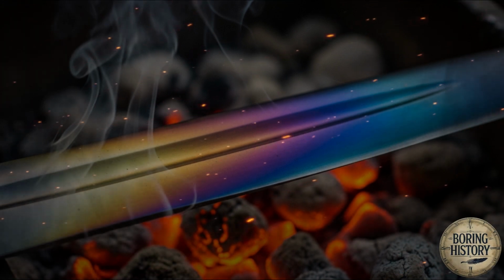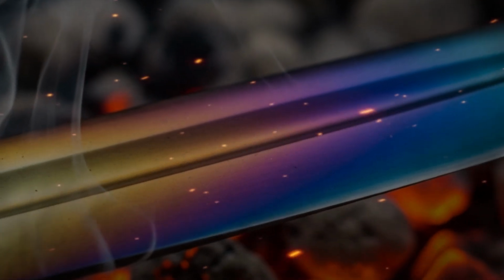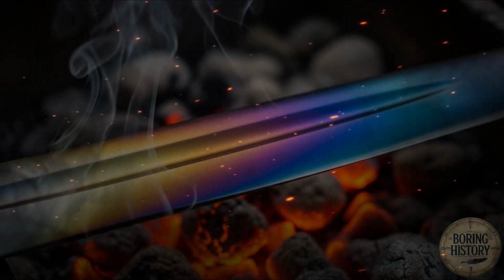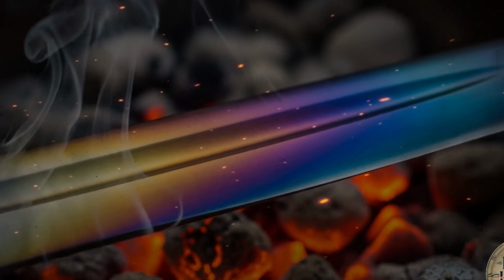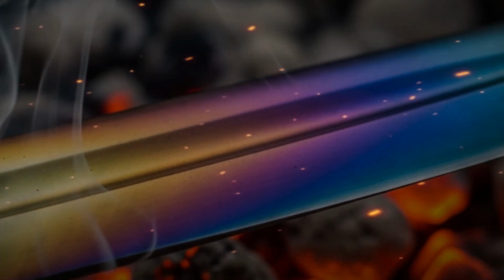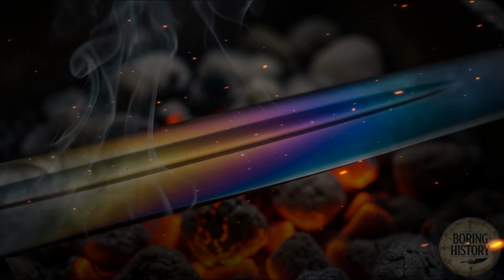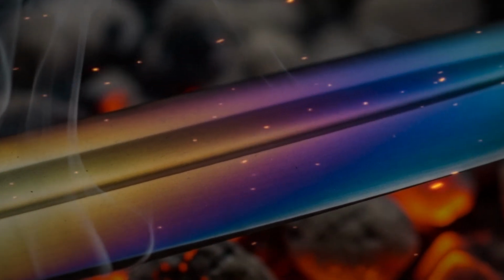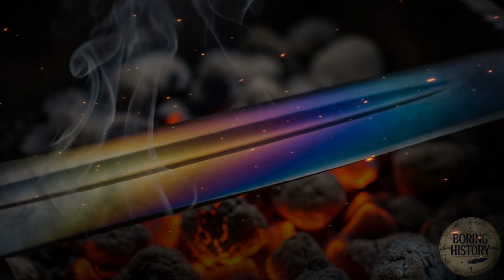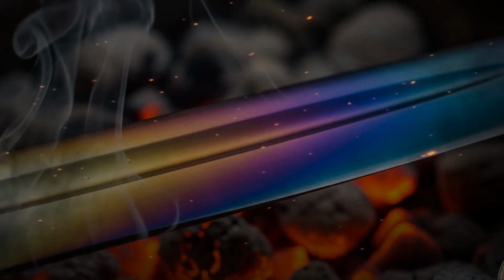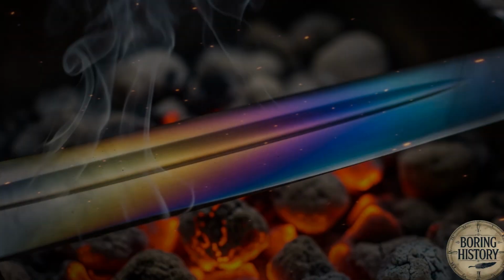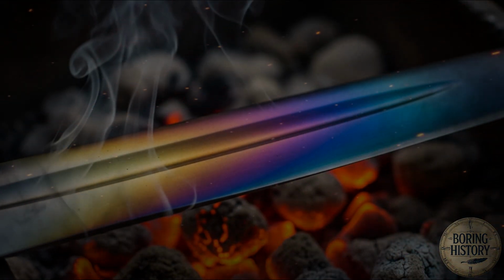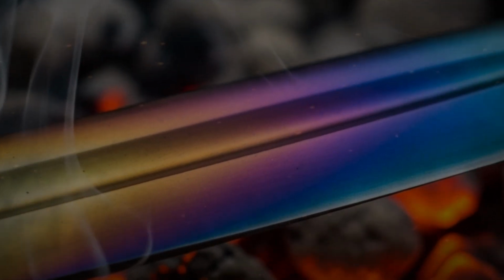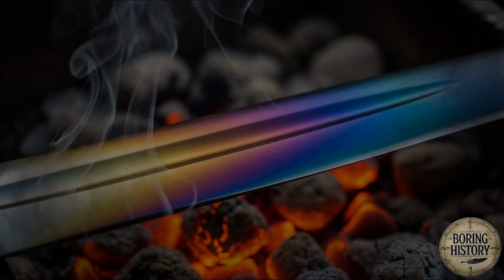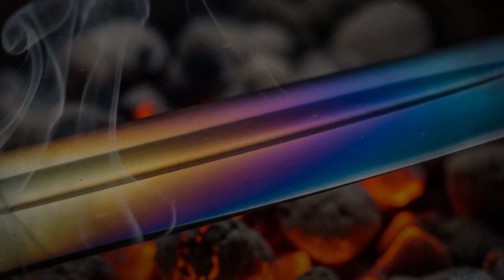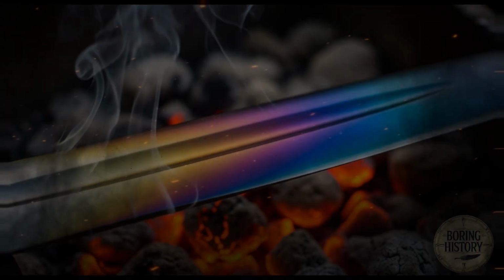Those were crucible steel, worked carefully to preserve and maximize the very quality that made crucible steel irreplaceable, its high, evenly distributed carbon content, which was what gave it the ability to harden, to take and hold an edge of a quality that no bog iron sword and no case-hardened European steel could match. The integration of these two different sections, the tough, flexible pattern-welded core and the hard carbon-rich crucible steel edges, was the moment when the Ulfberht became itself. Everything before it was preparation.